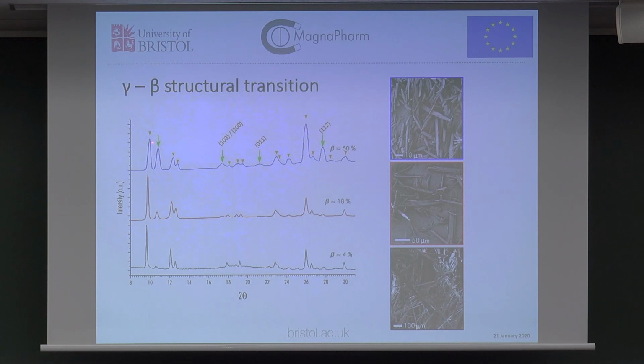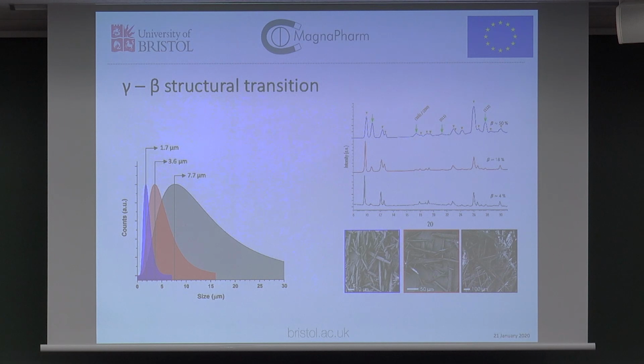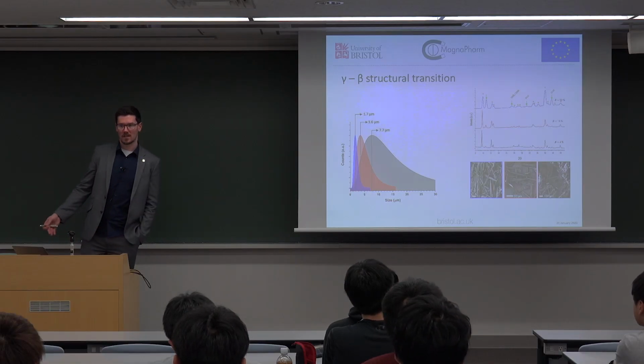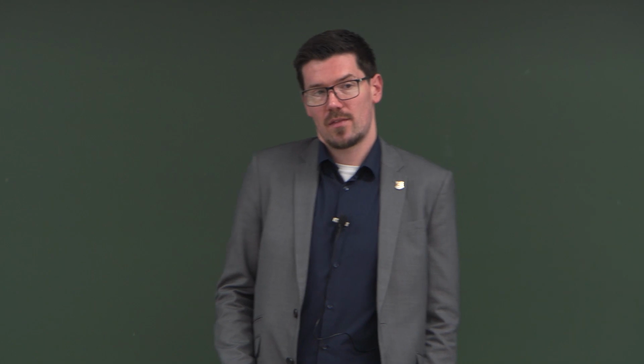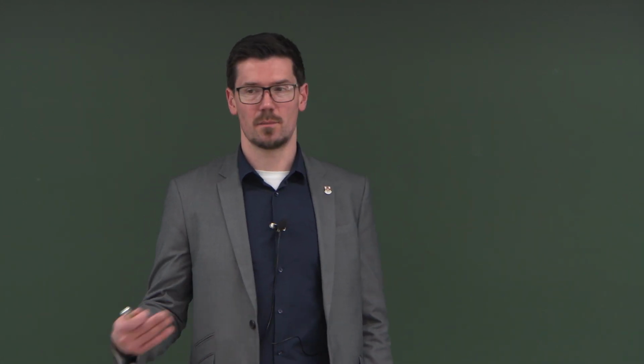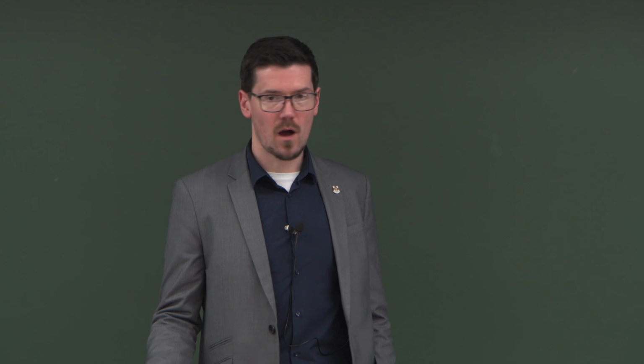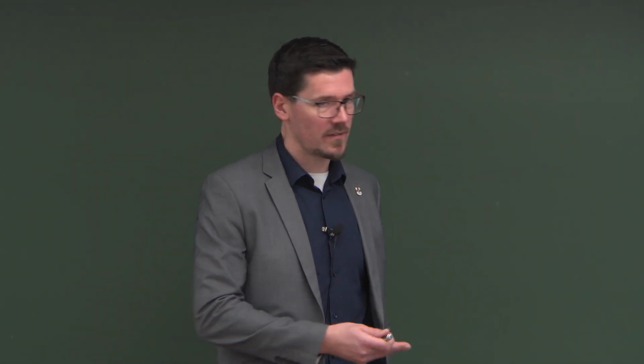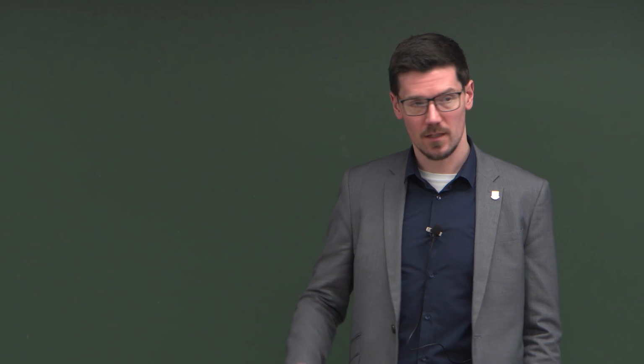The smaller crystals that I made, we ended up with a way greater conversion rate from gamma to beta. And the distribution of sizes of those crystals wasn't actually that great. So within that 1.7 to 7.7, somewhere we're going from 4% to 50%. So it does seem like size is a factor. It could be that the methods I used to make the crystals increase the number of defects, holes, impurities, but on the face of it, it looks like it's crystallite size that's having an effect.